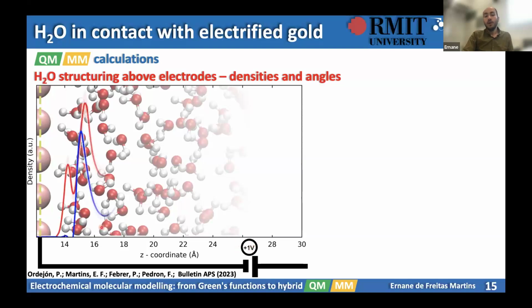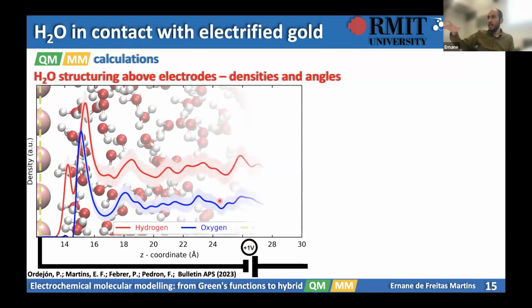I can plot the density distribution as a function of Z, as we go far from the surface, of hydrogen and oxygen separated. We can clearly see in the picture that some hydrogen atoms point toward the surface, and we can see this small hydrogen peak here. So the water molecules are responding to the electrified interface as we would expect.